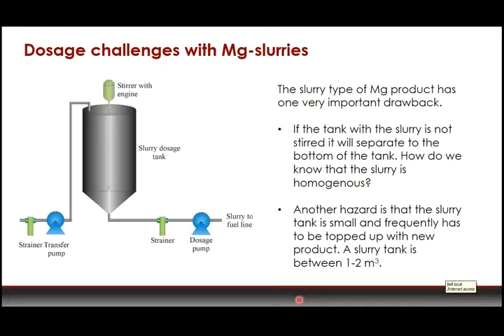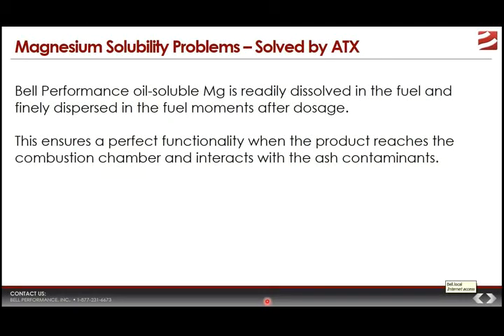Now, apart from the inconvenience of having a slurry dosage tank with a stirring unit in it, the other issue is that if you don't know that it is homogeneous at all times, then how do you know that you're getting the optimal amount of magnesium oxide delivered into the fuel oil? The short answer is you don't have a way to know that for sure. You just have to rely on your best guess. And that, unfortunately, is a drawback with magnesium oxide slurries.